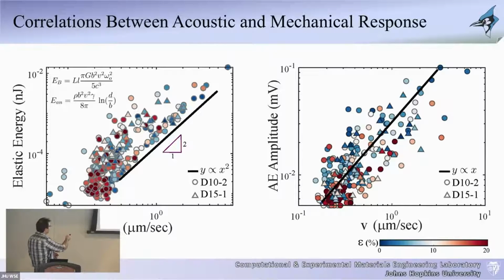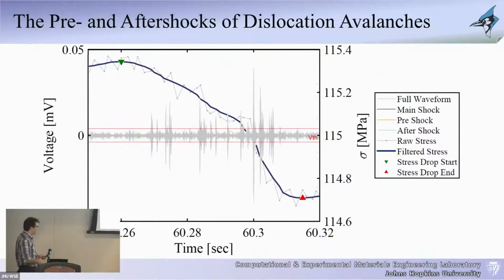So this is an example of the energy versus the velocity of dislocations, which basically says that the energy is potentially related to the square of the velocity. From our data, you can see that that behavior generally happens. You still get y proportional to x squared, but there's a significant amount of scatter in the data as well that these types of models do not represent. So the big question is, how do we take this type of representation, where there's a significant amount of scatter in the behavior, into these deterministic types of laws, which we think machine learning could potentially help us with, in trying to come up with a better understanding of these types of behaviors.